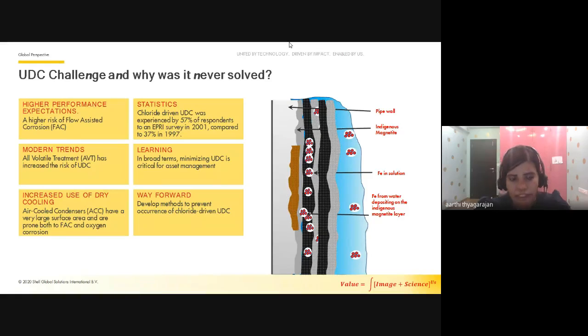Now, the third point, dry cooling. Concerns about industrial water usage have largely driven a trend towards increased use of air-cooled condensers, and these have very large surface area and are prone to flow assisted corrosion during operation and also air intake, and easily oxygen corrosion during downtime, etc. can happen. All of this has led to increased magnetite particles in the steam generator, and so it also leads to increased under deposit corrosion risk. Yeah, next slide please.